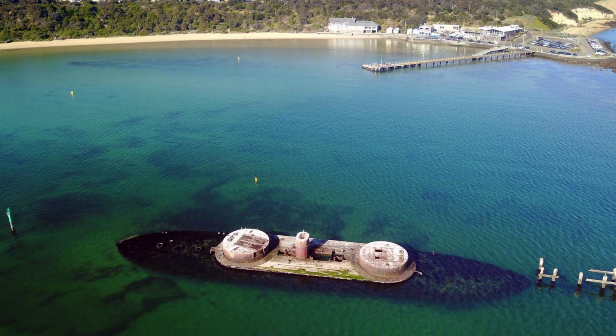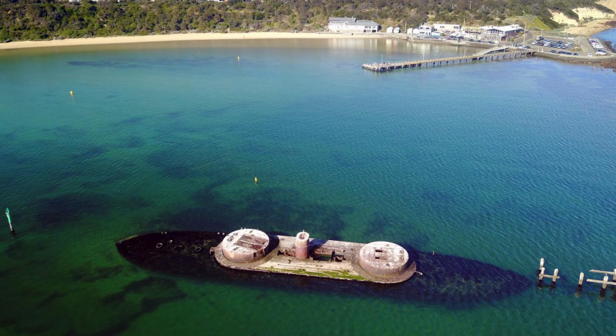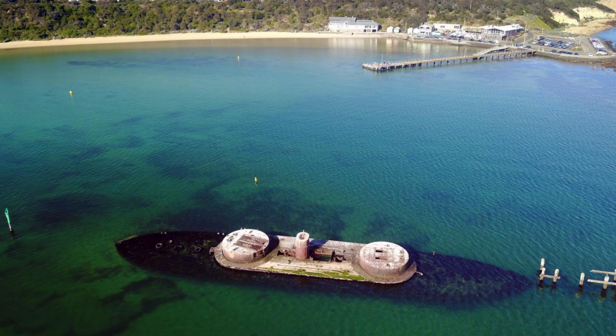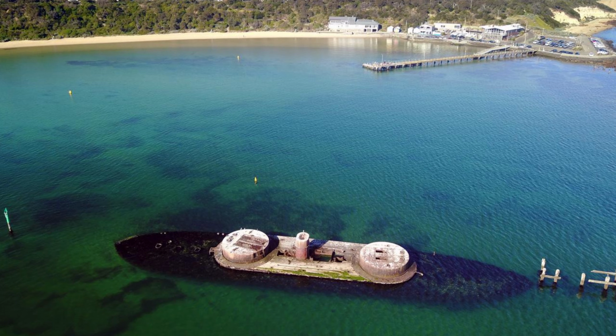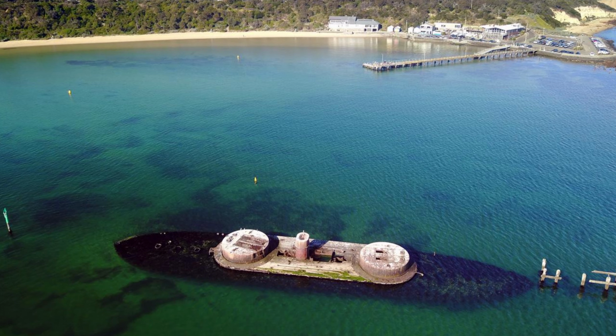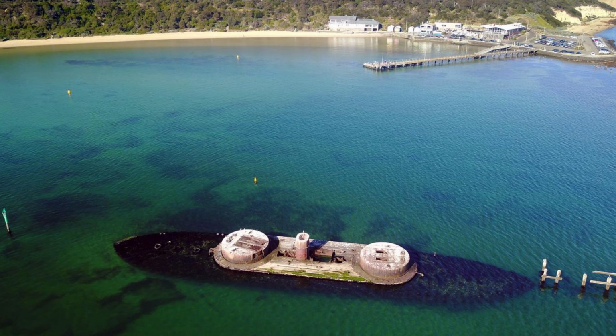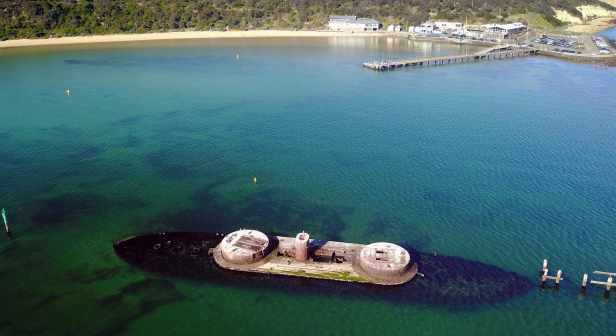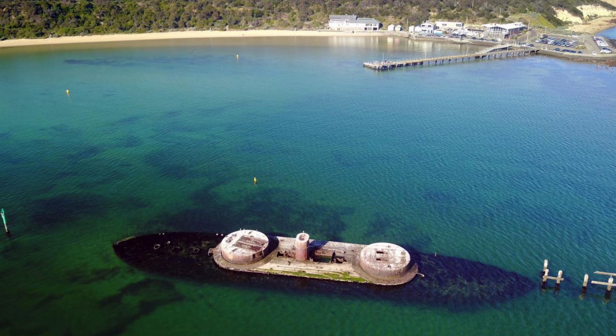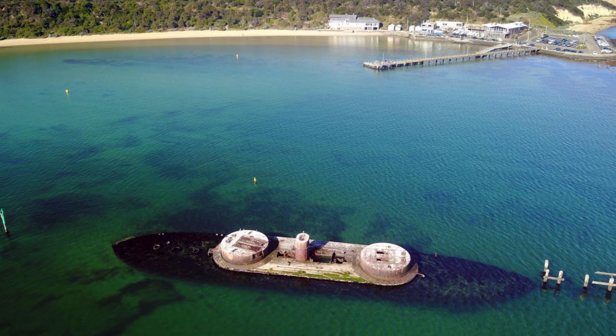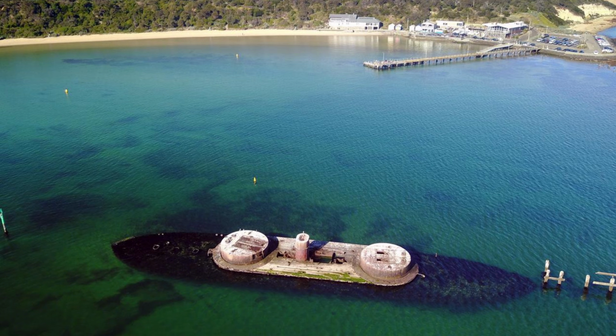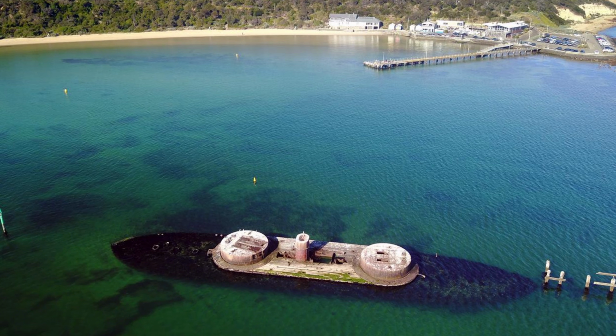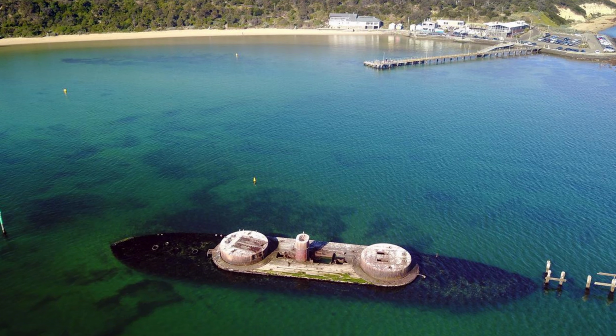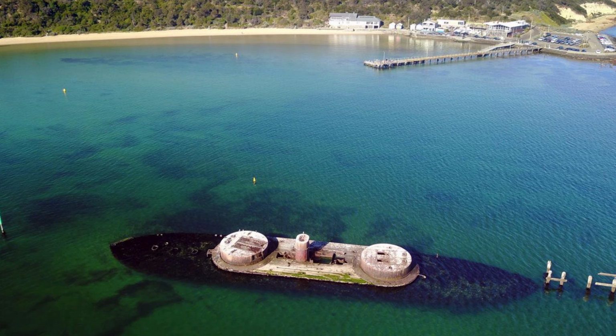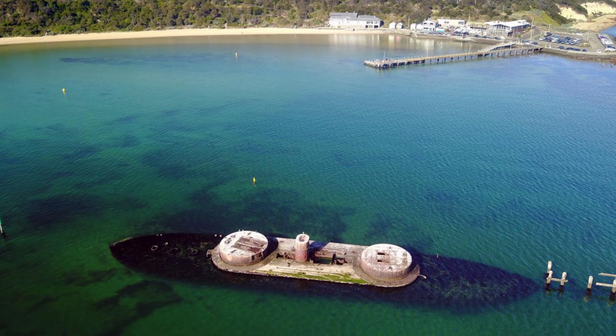The 2003 structural assessment proved that this localized iron loss had reached a critical and irreversible threshold. The survey data mapped by the remote instruments confirmed that the horizontal interior deck beams beneath the main guns were heavily compromised. Directly above them sat the fore and aft rotating gun turrets, immense masses concentrated on the weakest span. With the beams dissolving, that load had nowhere safe to go. The structure was already at its ultimate limit.